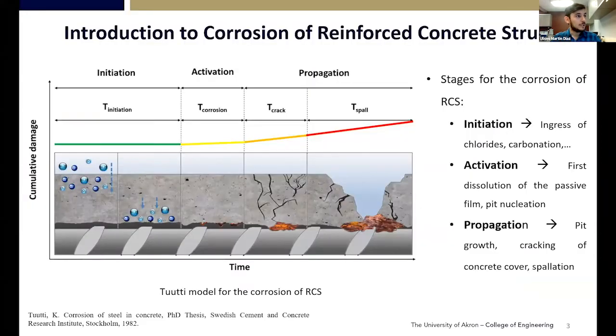So let's begin. In order to explain how the corrosion of reinforced concrete structures happens, the Tuutti model shows there are three main stages. The initiation, which takes the longest of all three, where the chlorides and the oxygen that are inside the electrolyte will migrate into the concrete by mass transport till they reach the passive film, giving way to the activation process, which starts by depleting the passive film and ends up getting to the rebar. Once these aggressive agents reach the rebar, they will start forming some oxide scales, which have a higher volume ratio than the steel, adding some crystallization pressure, which will exert some tensile stresses on the concrete.